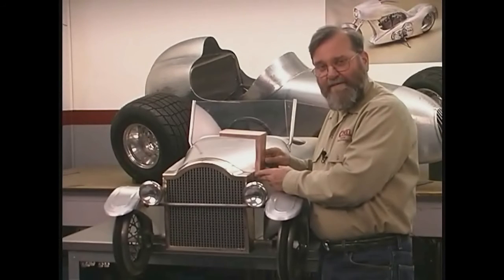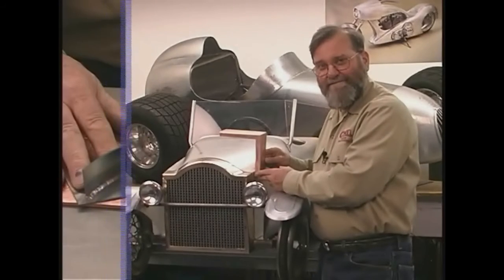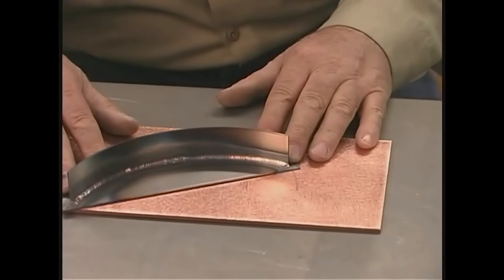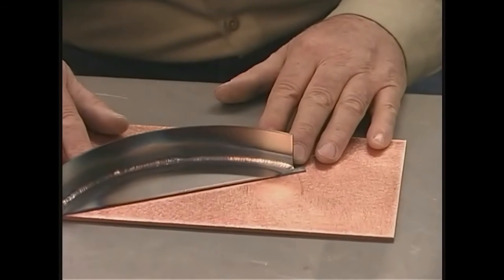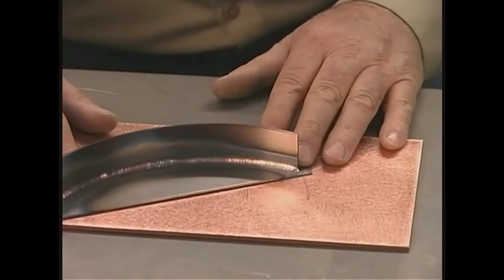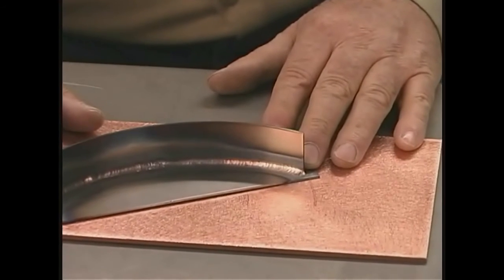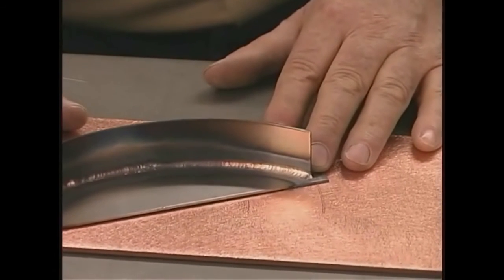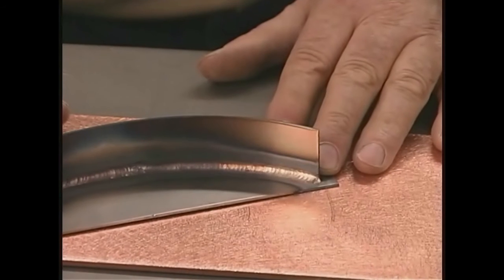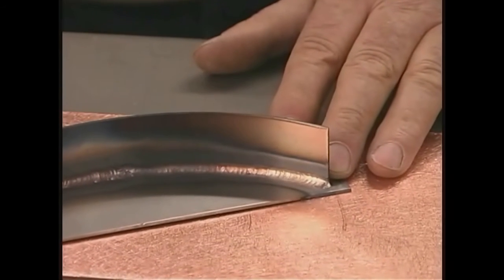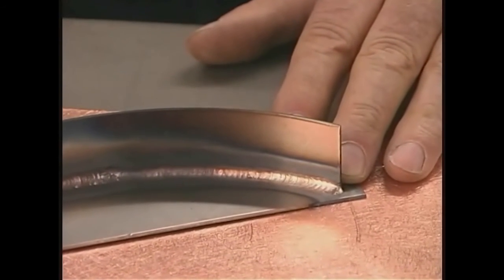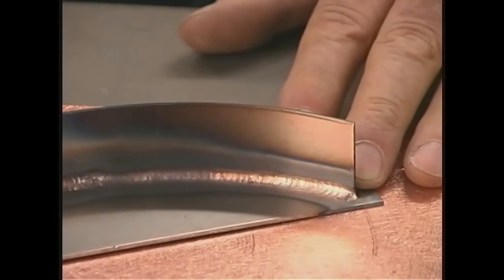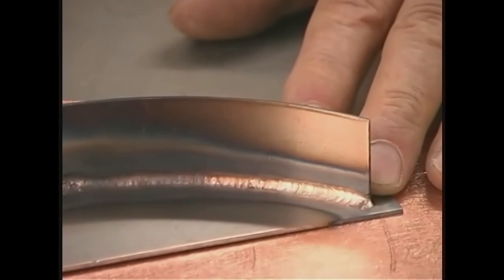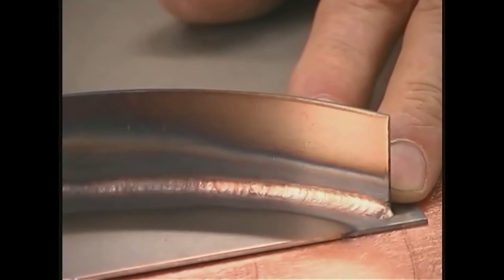Let's look at another application for bronze welding rod. Not only can you weld bronze with bronze filler rod, you can weld steel with silicon bronze filler rod. And there are some times when you might want to do that. To begin with, you need to understand that silicon bronze has roughly half the strength as steel, so it isn't a general purpose filler rod for steel. But in situations where you want to reduce the amount of distortion from welding, silicon bronze rod may help a lot with that.